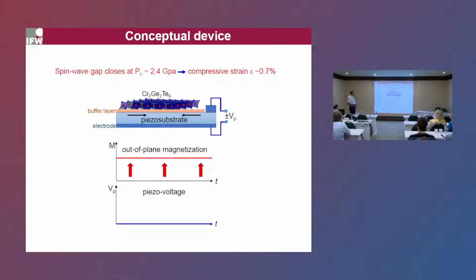interesting conceptual device when we put, say, this layer of chromium germanium telluride on a piezo substrate. If the substrate is unstrained, then we would have the time-independent out-of-plane magnetization of the single layer. As soon as we apply a voltage to the substrate, we contract the layer, and so the magnetization is lost. We can apply a new pulse, and it goes like this. And so this is an interesting potential functionality.